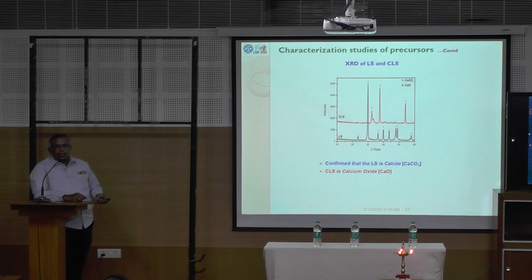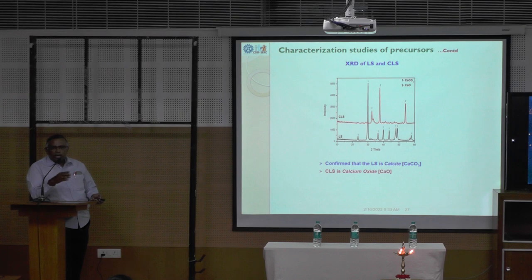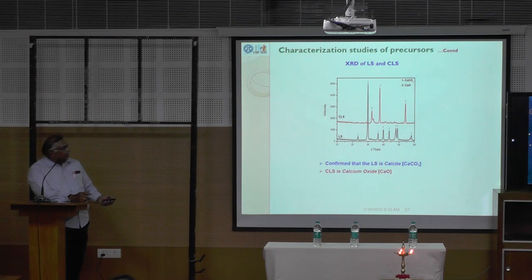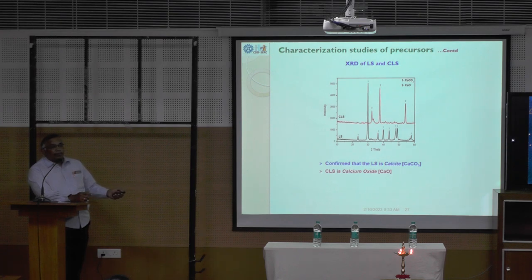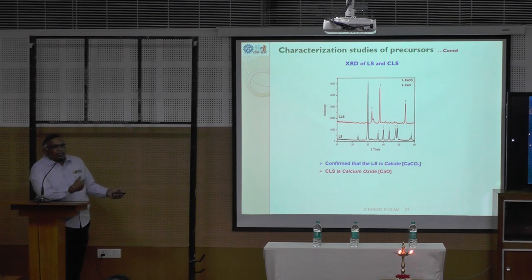This is X-ray diffraction. I am going to talk about X-ray diffraction, scanning electron microscopy, and thermogravimetry analysis — these are all techniques and tools for identification of the material. This is the XRD of lime sludge (LS) giving peaks like this. If I am heating it to a different temperature, the peaks are shifted — those peaks pertaining to calcium oxide. That is our material. Calcium oxide is required for our cement replacement.